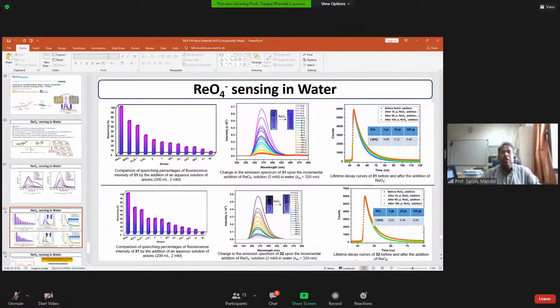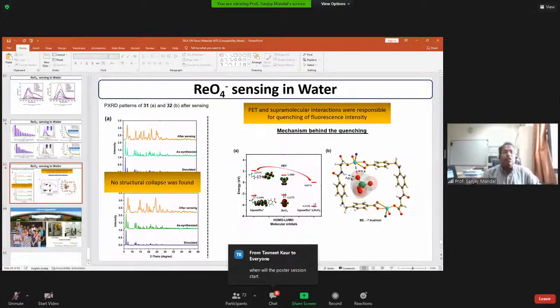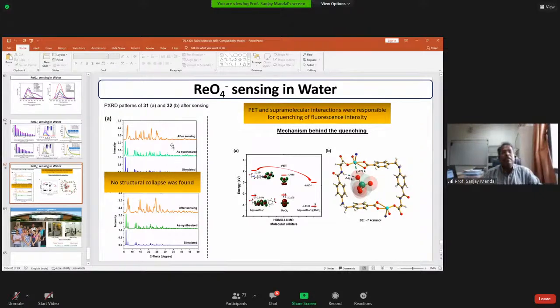And we looked at the mechanism where we find that the time resolved does not change the tau, that is the lifetime. So it is static in both cases. And based on the structural investigation by PXRD, you can see that as synthesized versus after sensing, there is no change. And based on the calculation, we see it is PET that is doing it. And here is the perrhenate interacting not only with the NH, which is expected to be very good, hydrogen bonding, but also the interaction with the metal center, and binding energy minus 7 kcal per mole.